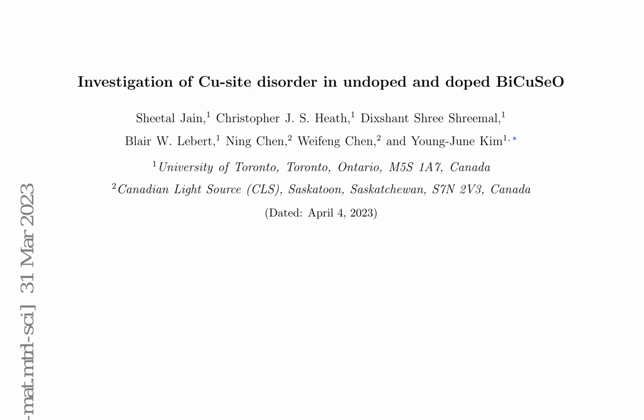This suggests that the significant disorder on Cu in the BiCuSeO crystal structure framework is retained by the Ag dopant on replacing Cu at that site, for all temperatures studied. This means that the disorder observed is actually linked to the Cu site, as opposed to just the Cu atom, since the Ag dopant retains the observed disorder.